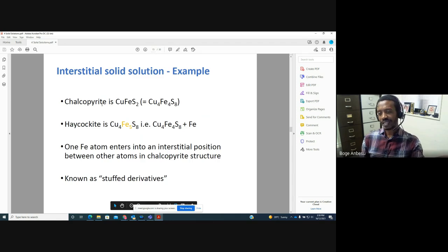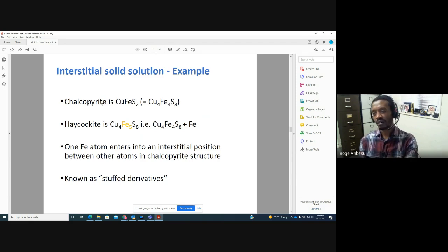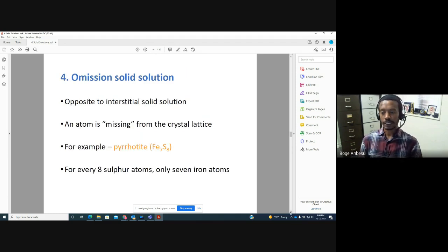For example, a good example is chalcopyrite and haycockite. It's believed haycockite is derived from chalcopyrite, but it contains one extra iron, as that slide shows. So chalcopyrite plus one extra iron gives you haycockite, but we don't know why that iron is sitting there. There is always extra iron, but that extra iron is not replacing the copper. We still have 4 coppers, and it's not replacing the sulfur because they're incompatible. The iron simply occupies a void position, a space, and that again can be found in nature and is considered an example of solid solution.